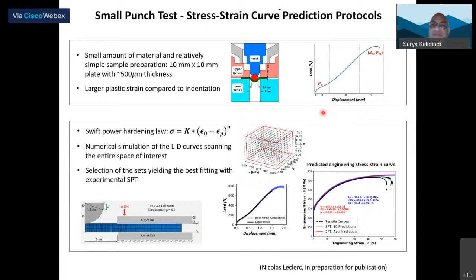The other technique we have been developing, and it's just very recently in the last couple of years, is the punch test. Again, people have been using punch tests forever, at least especially in the nuclear industry. So you get this load displacement curve. And then people have protocols that convert some of these to properties of interest, like yield strength, UTS, and so on and so forth. And just like the indentation methods, what we do is the other way around. We actually want to convert this to a stress strain curve.